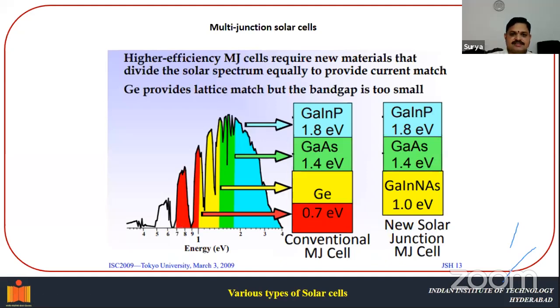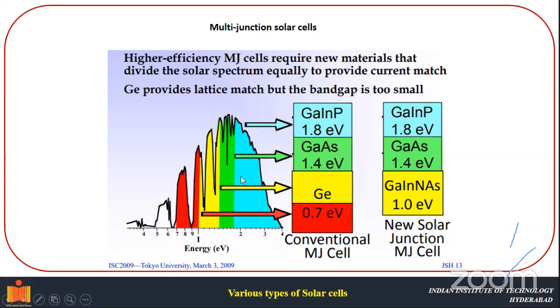multi-junction solar cells, they actually give higher efficiency. It is because of the fact that, as I mentioned, different materials will have different band gaps, and correspondingly the absorption of the sunlight will be different at different energies. Like for instance, if I consider gallium indium phosphide, it has a band gap around 1.8 electron volts. So this absorbs the energy from this region, whereas gallium arsenide will absorb the energy from this region, from the green region. The germanium will absorb the energy from this region.